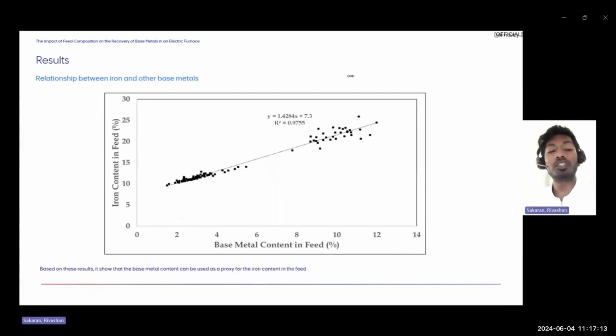So what we also noticed is that there is a relationship occurring in the concentrate between the iron content and the base metal content of the feed. As a result, we were able to use the base metal content as a proxy for the iron content in the feed, utilizing this formula as well.